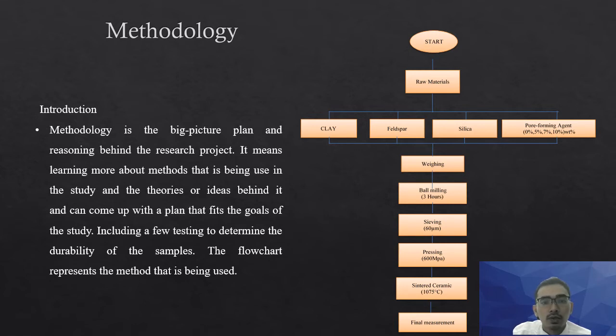Next, the mixture will then be put inside the bottle containing around 30 milling balls, which will be rotated for a duration of 3 hours. The function of this step is to grind the mixture to form a fine grain powder. The next step is to continue with the process of sieving, which is to separate the granulate powder from the fine grain powder.